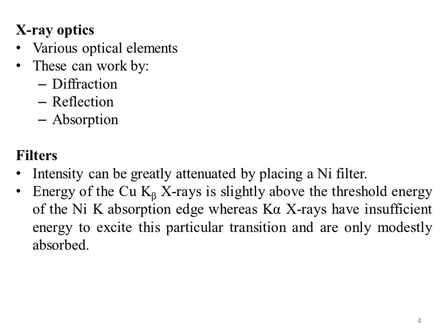Its intensity can be greatly attenuated by placing a nickel filter, a uniform thin sheet of nickel, in the beam path.